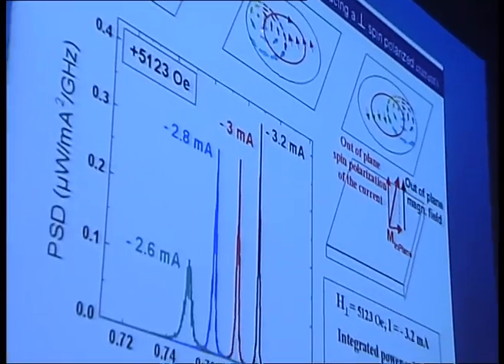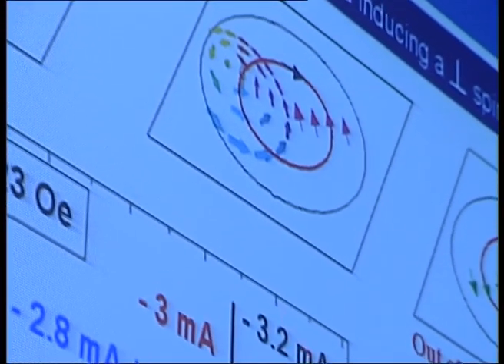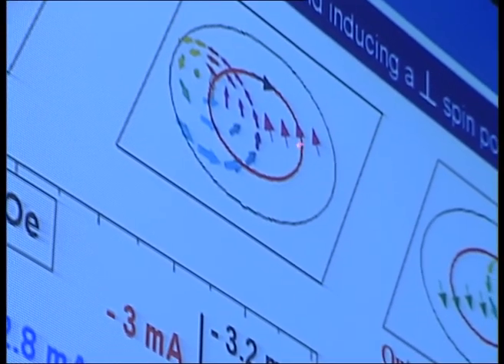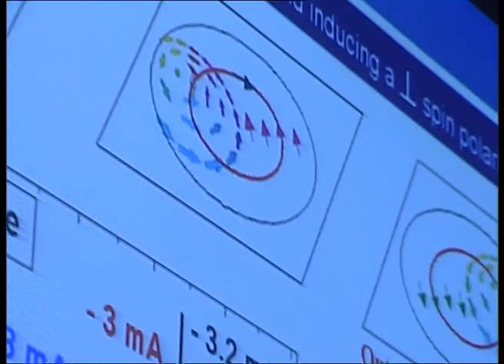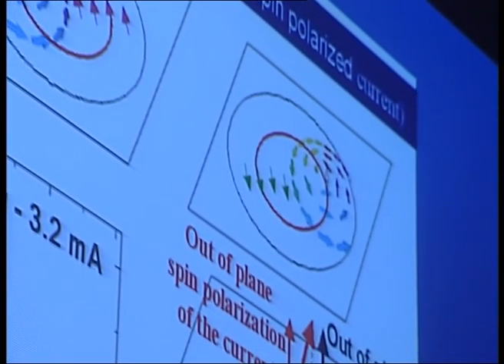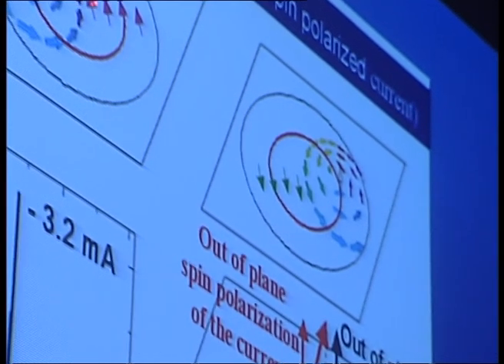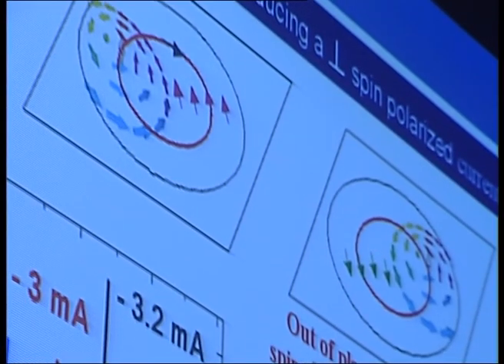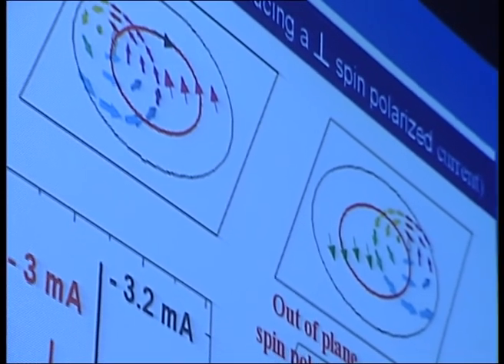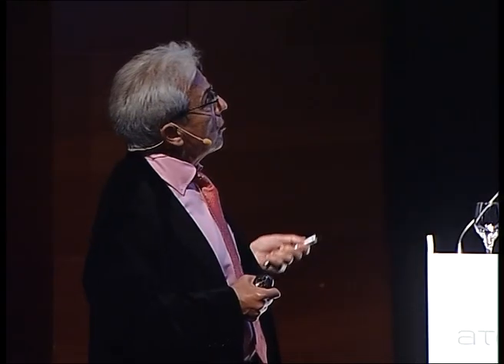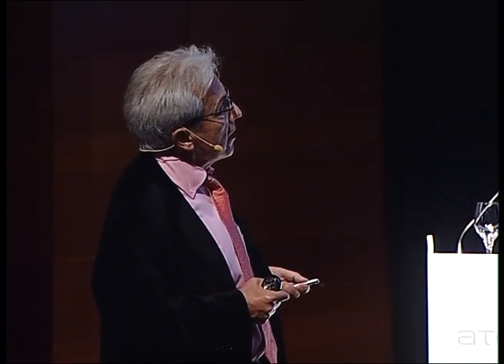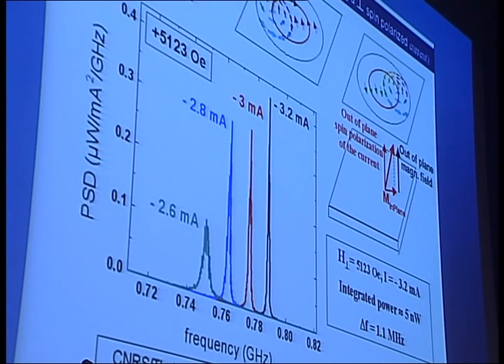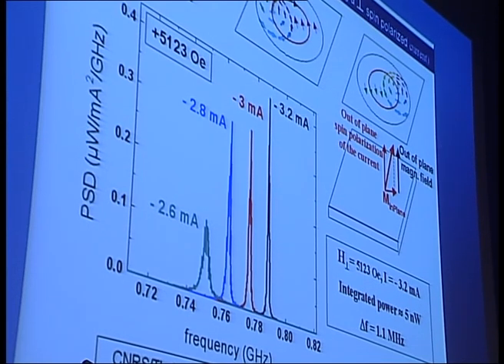The spin transfer torque will produce these rotations, so that when the vortex is on the left, for example, this means that in the major part of the dot the magnetization is in this direction, but when the vortex is on the right, the magnetization is in the opposite direction in the major part of the dot. That means there is a periodic variation of the magnetization, and of course this also produces a GMR or TMR effect and an alternating signal. You can see some spectra of microwave power produced by this emission, around 1 gigahertz, but now with very, very thin lines, which are very appropriate for applications. So the progress has been significant in this field.